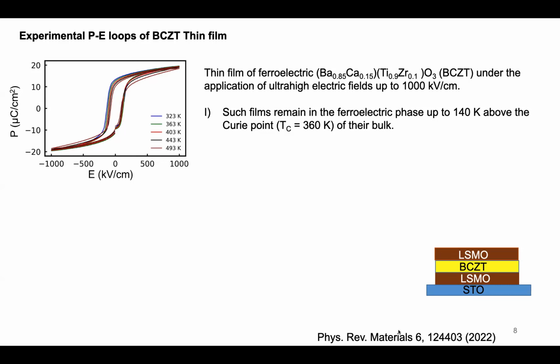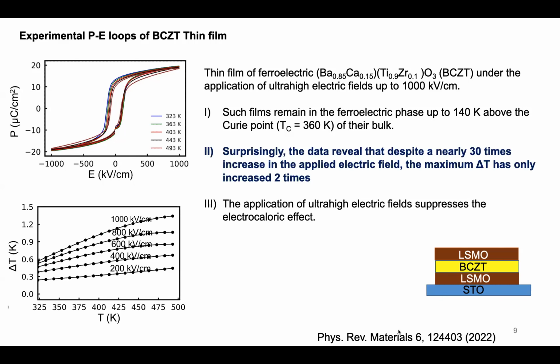We know the phase diagram of zirconium versus temperature, and we know the TC of those different concentrations. And for the 10% zirconium concentration, the TC is around 360 Kelvin. But we know that the TC changes with the thin films also, but that's not the case here. So when they applied a field up to 1,000 kV per centimeter, the loops are still kind of a ferroelectric one.